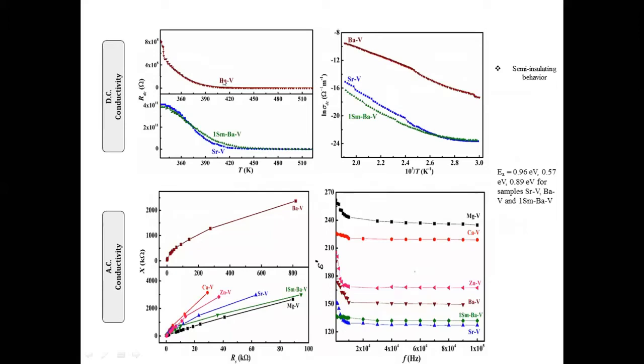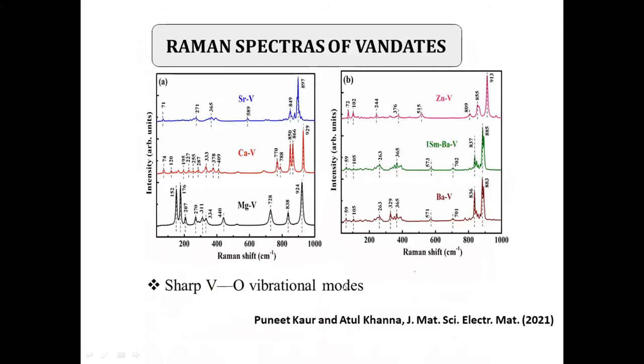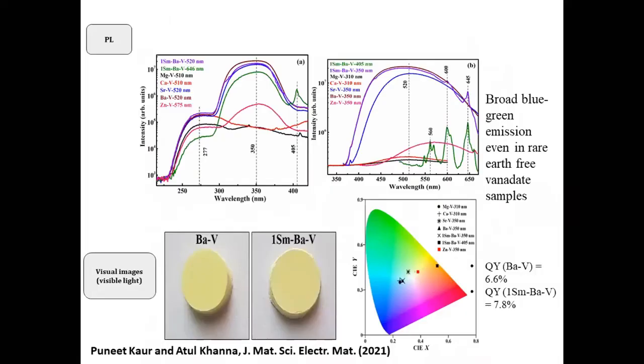And if you increase the temperature, resistance falls drastically. These are the impedance or the LCR measurements, and their dielectric constants are also fairly high, around 180 at frequency of about 1 kilohertz. And these are the Raman patterns of vanadates. The vibrational bands are mostly due to vanadium-oxygen stretching and bending vibration modes. And we see very good green light emission from these vanadates. You can see this is the excitation spectra, and this is the photoluminescence spectra shown on the right. We see very strong, very intense, although it is a broad band, around 520 nanometers. So I can convert blue light into green light.